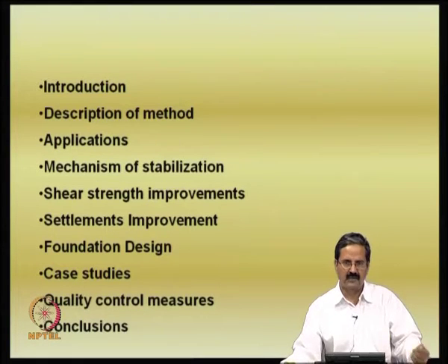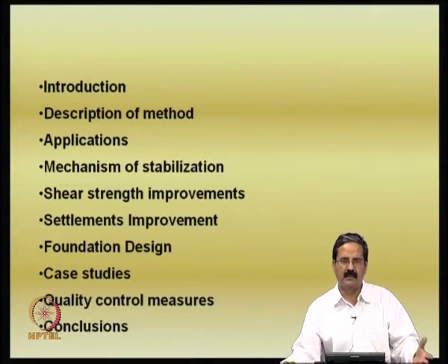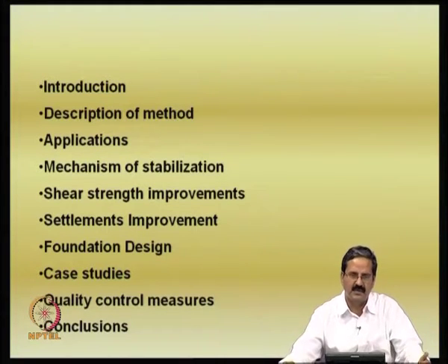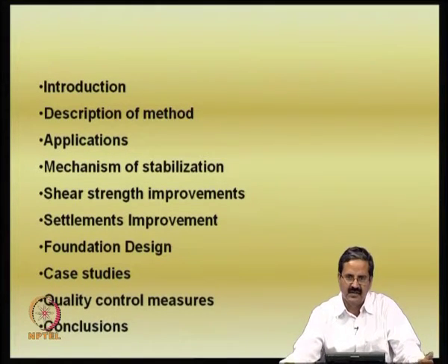People have shown that if you have sulphate material in the soil and you try to give a lime treatment, it cannot be effective. So if you want lime treatment to be effective, you should check if sulphate is there. If it is not there, then you go ahead with the lime treatment. Sometimes you also need to add additives like fly ash or cement, depending on the requirements.